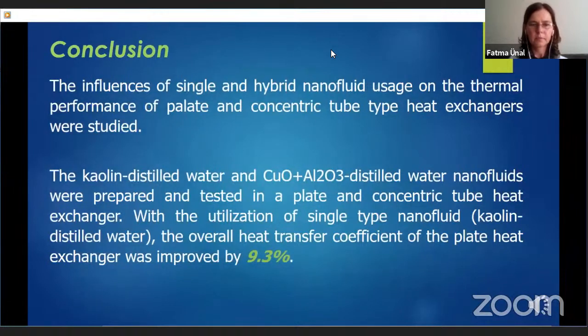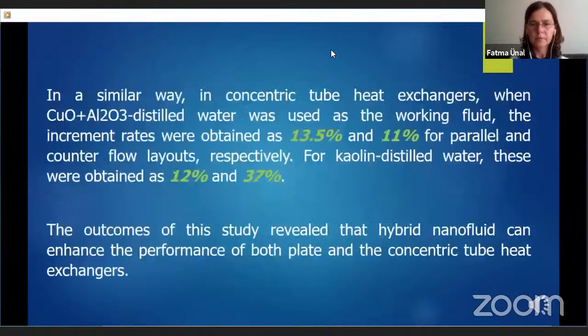As a conclusion, the influences of single and hybrid nanofluid usage on the thermal performance of plate and concentric tube heat exchangers were studied. The kaolin distilled water and copper oxide alumina distilled water nanofluids were prepared and tested in a plate and concentric tube heat exchanger respectively. With the utilization of single type nanofluids, the overall heat transfer coefficient of the plate heat exchanger can be improved up to 9.3%.